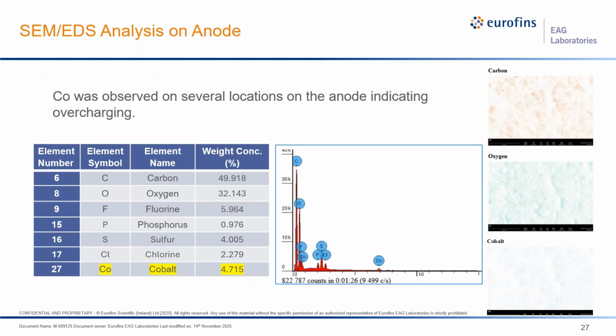Because instead, if there is overcharge, the opposite will happen. This time, cobalt will start to diffuse through the system, dissolve in the electrolyte, be carried towards the anode, and be redeposited on the anode side. As you can see from this image and this analysis, there is cobalt presence in the anode, which shouldn't be the case in ideal operation. That's why this suggests that overcharge is the main issue for this battery to swell.